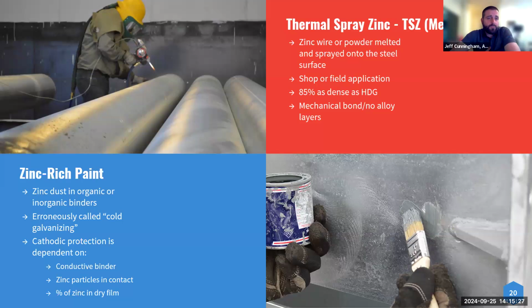So zinc thermal spray is pretty much the closest you can get to galvanizing without galvanizing. It's also called metallizing. Zinc wire or powder is melted and sprayed onto the steel surface. In the shop or field, you can do either. It's only about 85% as dense as hot dip galvanizing, and once again, it's a mechanical bond, no alloy layers. There's no fused together, no metallurgical bond. It is quite expensive as well.